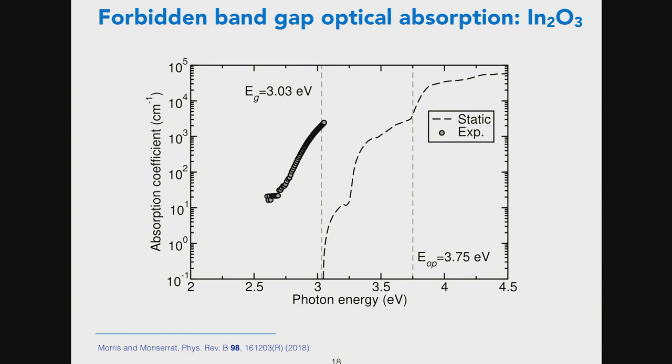band maximum, and that's because although the state at the gamma point can be definitely classified in terms of parity, as soon as you move a little bit away from the gamma point, then parity is no longer a good quantum number, and therefore you get some contribution from the other parity. And although the states are still largely aligned to the parity of the gamma point, you still have some transitions, and that's what this represents.